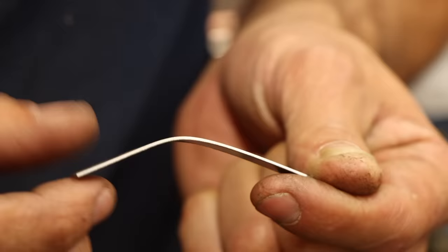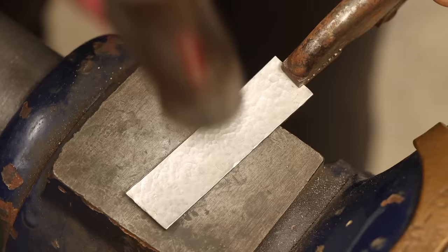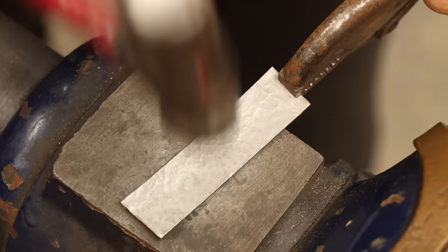I still have some leftover stainless steel sheet scraps from the original project years ago. But as you can see, the steel in its basic form is pretty ductile and bends easily, which is the opposite of how a pen clip should be. To fix this, I'll use the same method I did back then and work-harden the steel by peening it with a ball-peen hammer. This raises the yield strength of the steel, allowing it to flex a bit more without permanently bending, while also leaving a cool hammered finish.